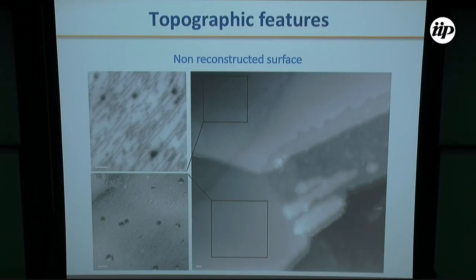The image on the right is the whole scanning window. It's an image of 2 microns with a corrugation of less than 2 nanometers. So it's really flat. It's atomically flat. When we zoom in, we see 2 different kinds of surfaces, which essentially consist of missing rows and remaining rows, most likely of calcium or potassium atoms.